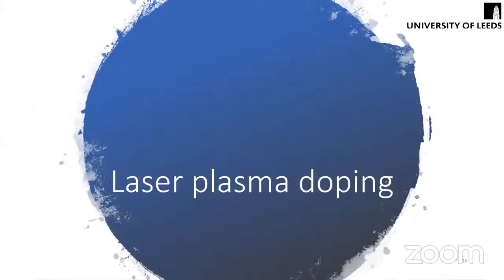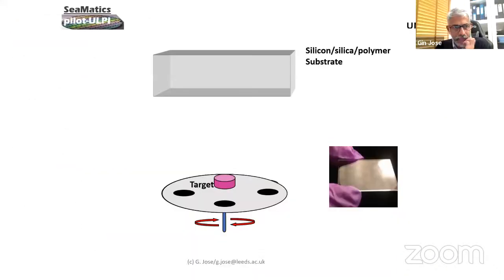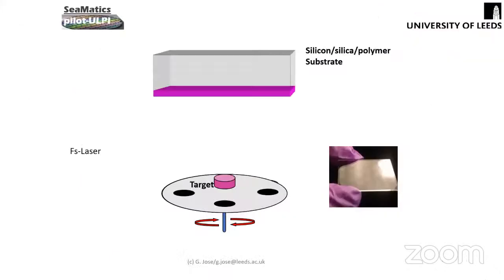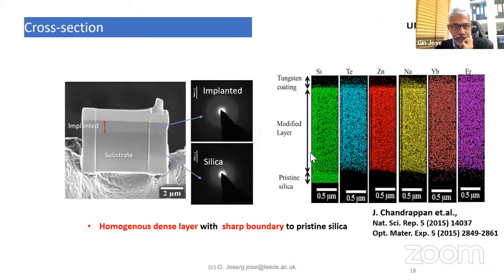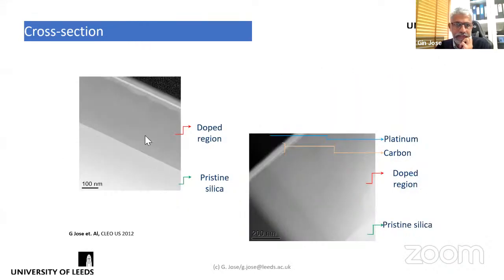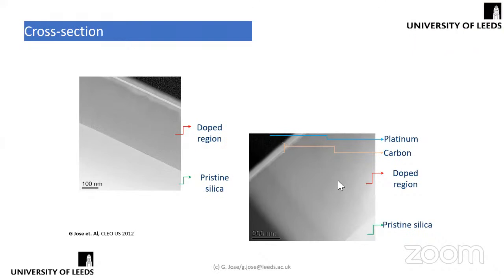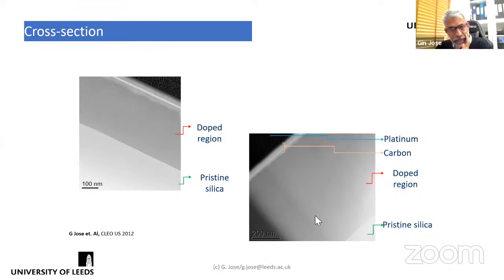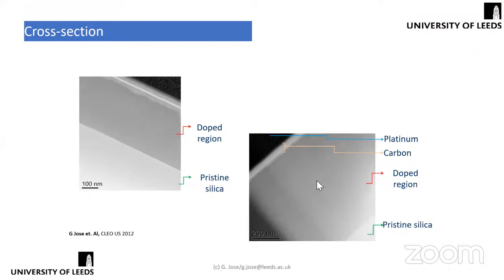So this is all done in a vacuum chamber. In terms of the doping process, the homogeneity is quite good. Simply looking at even the cross-section image, you don't see any detectable clustering. It's a STEM image? This is a TEM image. TEM, okay, fine.